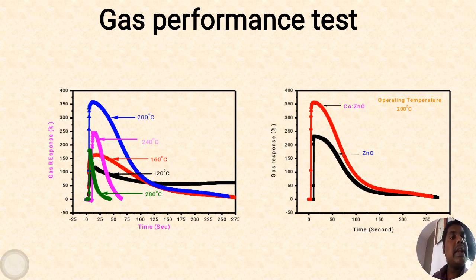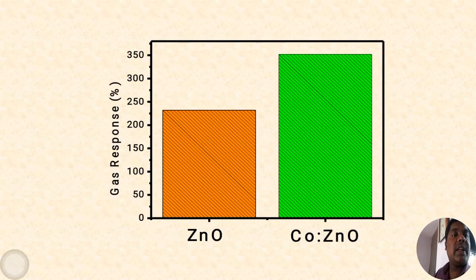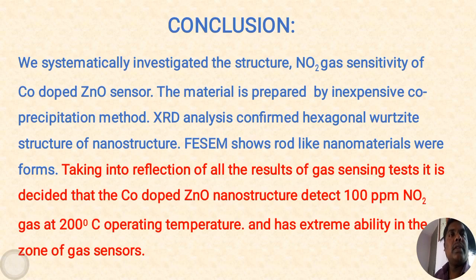Now see the second graph. In the second graph we checked pure zinc oxide nanostructure and cobalt doped zinc oxide nanostructure at operating temperature 200 degrees Celsius and NO2 concentration of 100 ppm, and we get the result. Cobalt doped zinc oxide shows the maximum gas response as compared to zinc oxide. Why? This is due to increased surface area as well as increased grain size, which is very attractive for gas sensing performance. Now here is another diagram for zinc oxide and cobalt doped zinc oxide. Here is a clear-cut indication that cobalt doped zinc oxide shows the maximum response as compared to zinc oxide gas response.